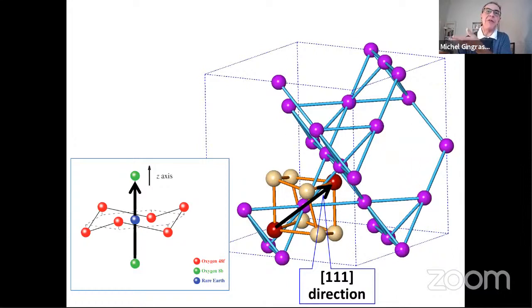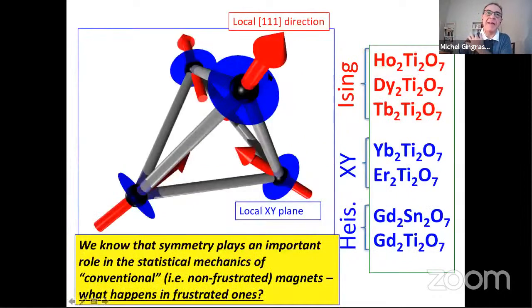And so one refers to this as a local anisotropy, which can be either Ising-like, as marked by the red arrows on this picture, or XY-like. This is another interesting aspect of these systems. Depending on which ion you have, you have access to either an Ising model or an XY model. And spin ices are realized in the extreme Ising limit of holmium and dysprosium.